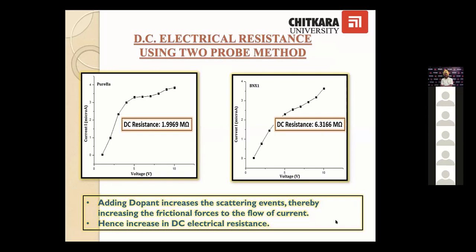Again we found results favorable to the previous ones. First we found that when you change from bulk to nano, the DC resistance increases. Then we added certain dopants, and we found that adding dopants increased the scattering events, thereby increasing the frictional forces to the flow of current, and hence the DC electric resistance increases. So if you take these two slides jointly, the electromagnetic wave consists of electric and magnetic fields, and both kinds of losses are increasing when you change a bulk material to nanomaterials.